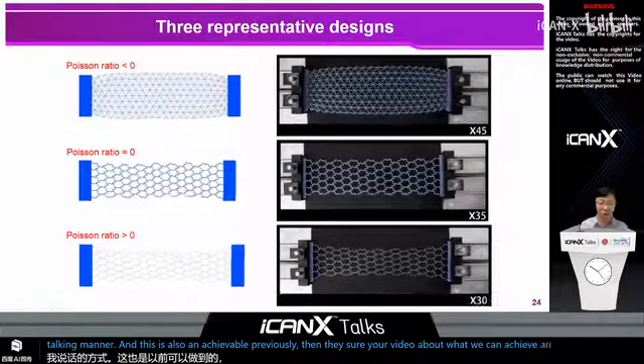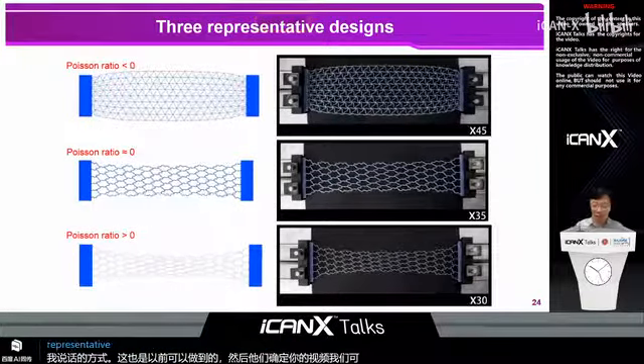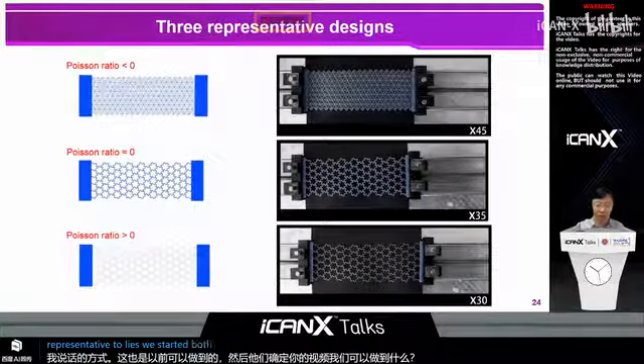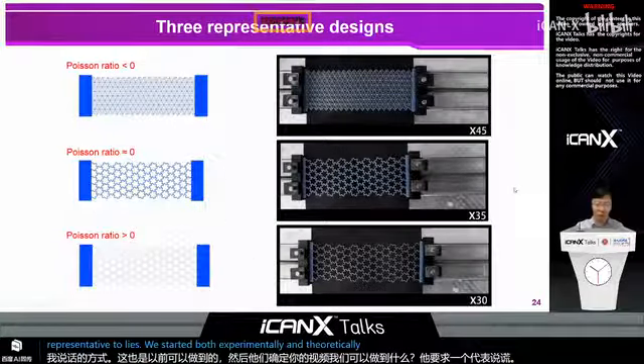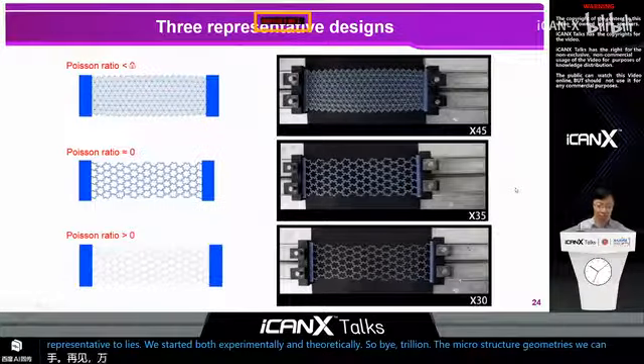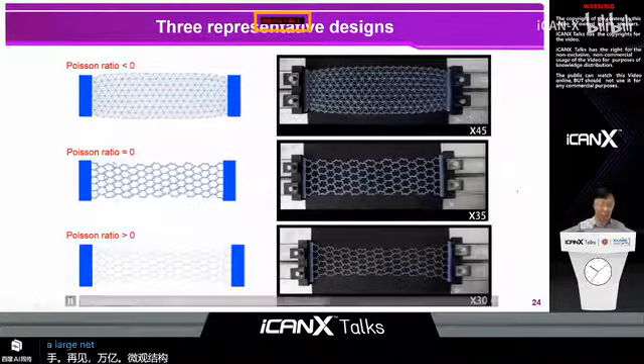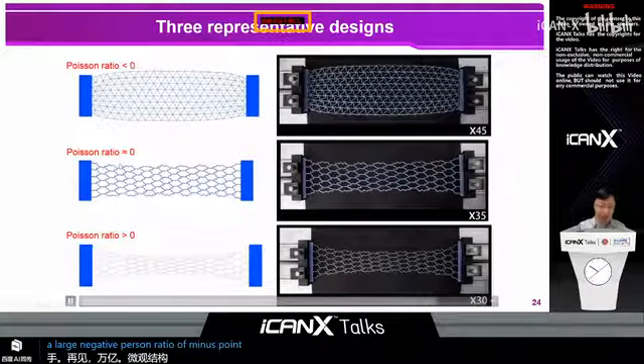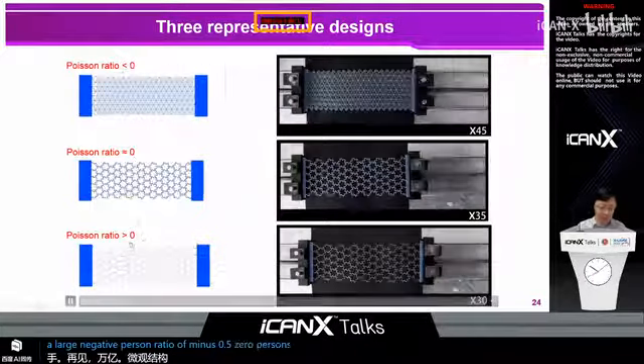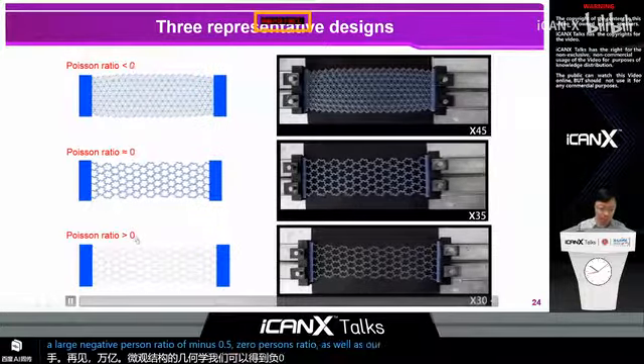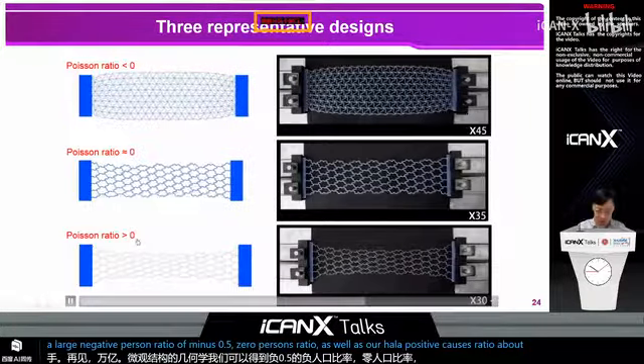And here are 3 representative designs we studied both experimentally and theoretically. So by tuning the microstructure geometries, we can achieve a large negative Poisson's ratio of -0.5, 0 Poisson's ratio, as well as a positive Poisson's ratio of about 0.5.